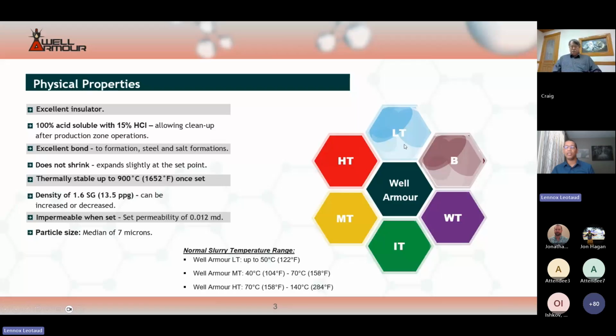LT stands for low temperature, and a typical low temperature slurry can be used from all the way up to 50 degrees C. Well Armour MT is the medium temperature component, and a typical slurry for a mid-temperature application is Well Armour MT plus the Well Armour B component. And the Well Armour MT can be used from 40 C to 70 C. The Well Armour HT slurry can be used from 70 C to 140 C. And this is just provided here as a guideline. In some cases, to achieve the set time targets, you can combine the LT with the MT and the B to achieve a particular set time. You can also combine a MT with a HT component to achieve a particular set time as well.